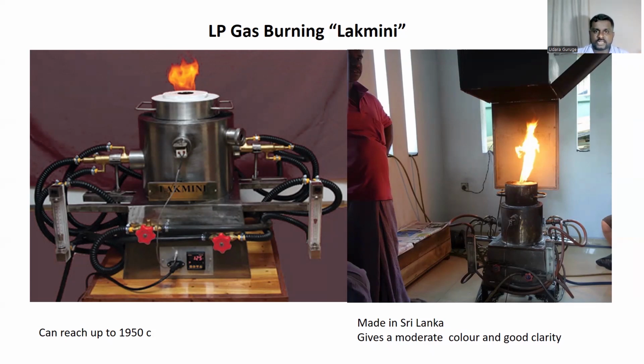This furnace uses LP gas with oxygen to ignite the fire or to maintain the fire. From this furnace, you can go up to even 1950, even 2000 Celsius. But it is not recommended to go over 1850 because, as I already mentioned, it can create certain fractures: the higher the heat, the higher the chance of bursting the stone. This is a product designed and made in Sri Lanka. Now even Thai people use this machine for gem burning.